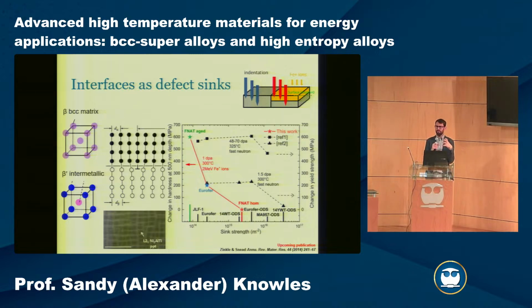So this is quite a profound result. Normally when you irradiate a material, you create defects, they strengthen the material, but they harden and embrittle it. It's quite unusual. It's only really in these ODS materials and these ferritic superalloys where we've seen this almost nil apparent irradiation hardening. So we're quite excited about this result in terms of being able to develop more irradiation resistant materials.